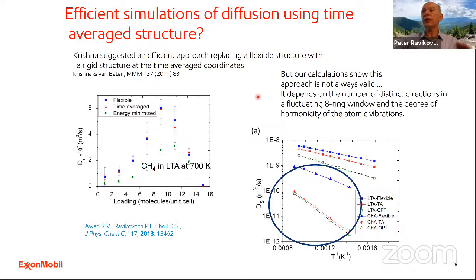So if the crystal vibrates harmonically, in other words, at all temperatures it is essentially the same structure, then the effects of flexibility, if you take the average structure, will be equal to the crystallographic rigid structure. However, if the crystal vibrates anharmonically, then the flexibility will change the nominal window dimensions quite substantially. So that's the difference.